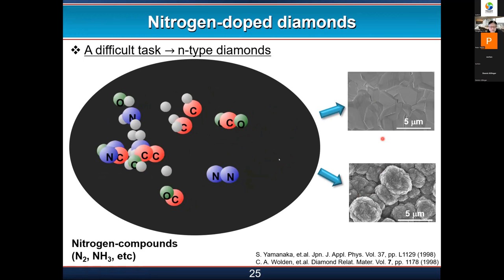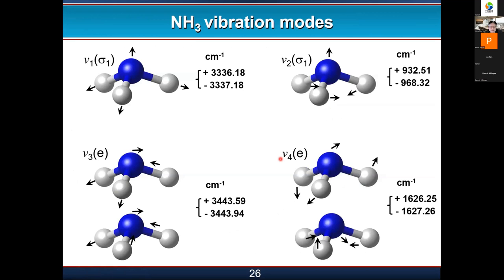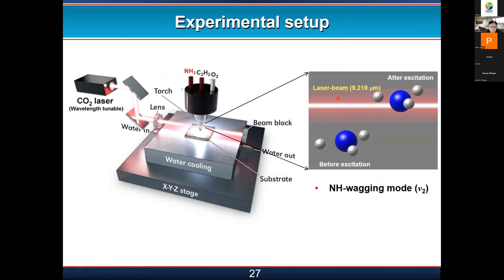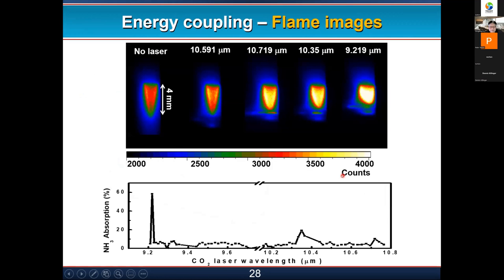So what we did was to use the CO2 laser to resonate the ammonia molecules this time, and we found one ammonia wagging mode which matches one line of the CO2 laser emissions. Instead of ethylene, we put ammonia here, and also shine the laser with a wavelength of 9.219 to match the wagging mode of the ammonia. Again, it's similar to what we did to resonate ethylene molecules. When we have a resonance, we see the flame becomes shorter and brighter, reflecting more active and faster chemical reactions. There is one strong resonance for the ammonia molecules at 9.219.